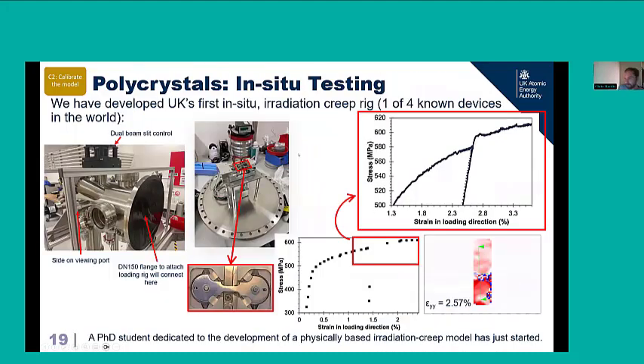And then finally, as I mentioned before, we're really focused on the influence of irradiation because that's the bit that we must understand the best in order to predict what will happen in a fusion irradiation environment. So we've made some progress in developing a bespoke rig that is used at the Dalton Cumbria facility, the proton ion beam. Here is a chamber with a load frame that we can attach to the beam line. And as such, we can have a tensile specimen at temperature and under stress, and we can irradiate that and observe what happens. So this has only just been built and is largely commissioned.